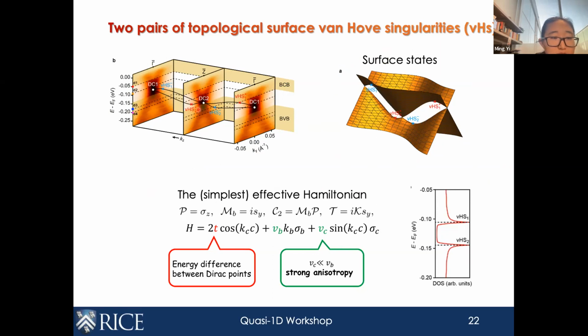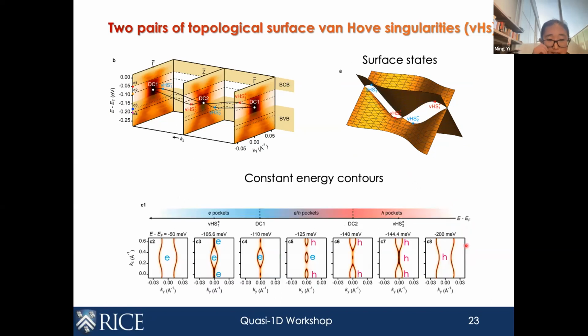So if we have the two Dirac crossings, that means that we will have this kind of set of surface states that includes, in addition to the two Dirac crossings, also two sets of Van Hove singularities here. And I just want to mention that we can identify the location of these based on the measured location of the Dirac cones, and also the measured Fermi velocity of these Dirac cones. And because these Van Hove singularities are surface states, they have divergent density of states, as shown here. And Fan has already indicated that this would give a host of very interesting Lifshitz transitions, which is shown here.